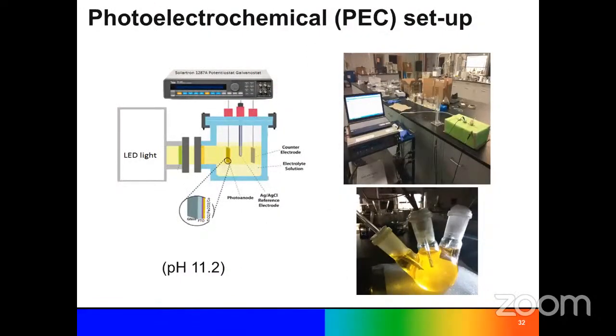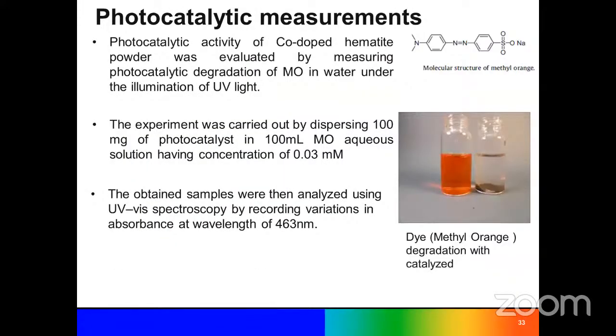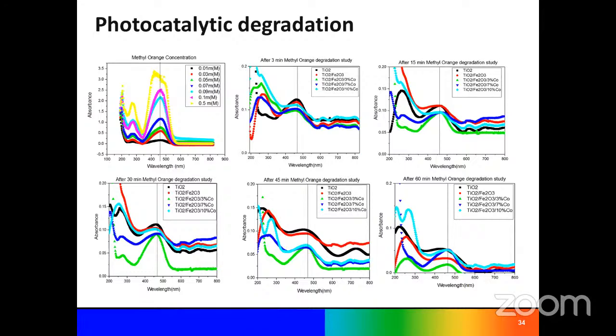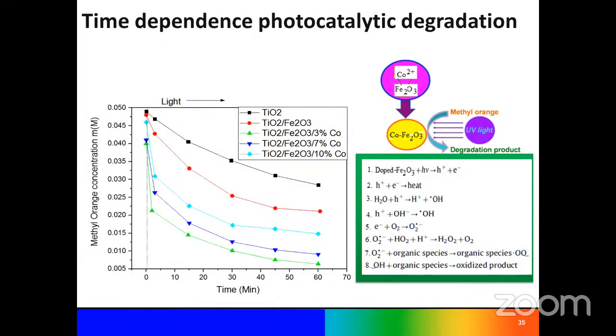And this is the setup we used, the AutoLab system, cyclic voltammetry and all the other instruments. This is the 3 electrode setup, with counter and working electrode as well. And then finally we checked its properties. But before that, we also checked whether 3% cobalt doped is giving the maximum efficiency and maximum absorption. That's why we did the degradation study with methyl orange. And here also we found that 3% cobalt doped is giving the maximum degradation of the wastewater in the presence of photon response. So it's concluded that 3% cobalt doped is giving the maximum absorption in the presence of photon response.